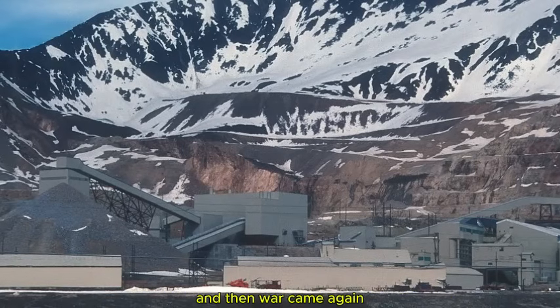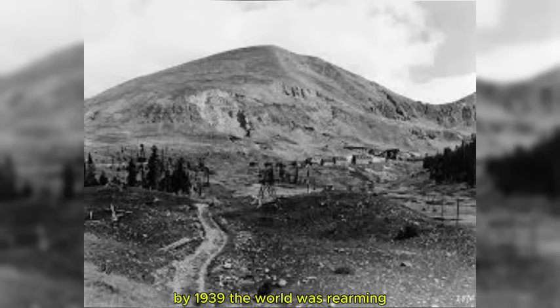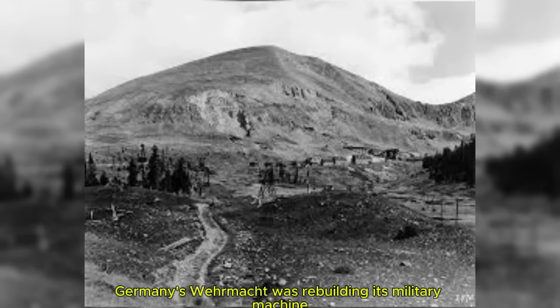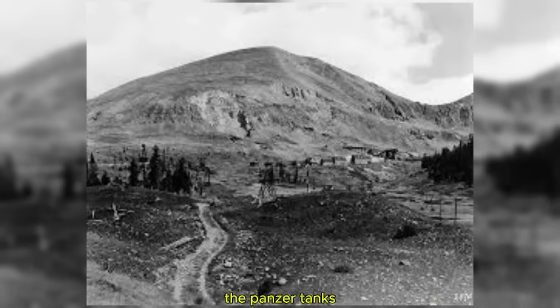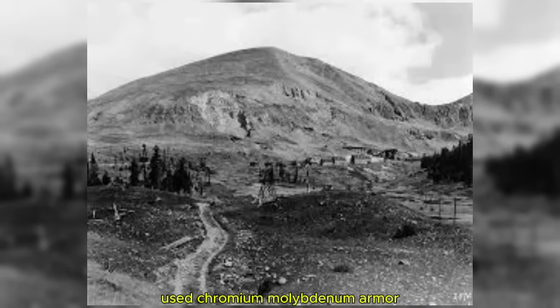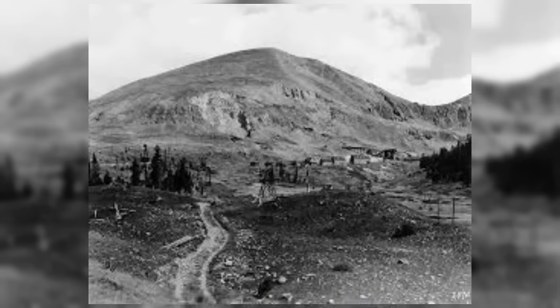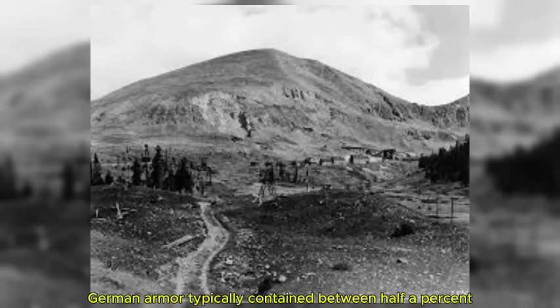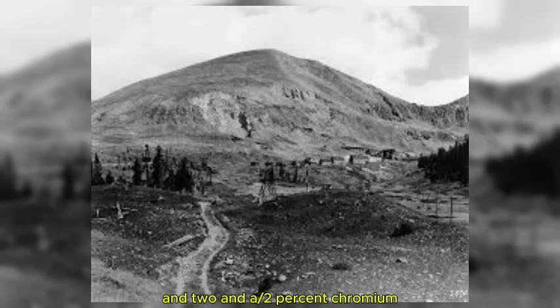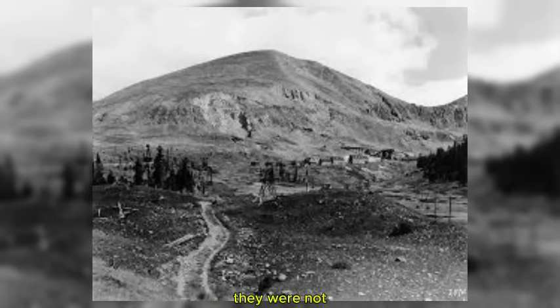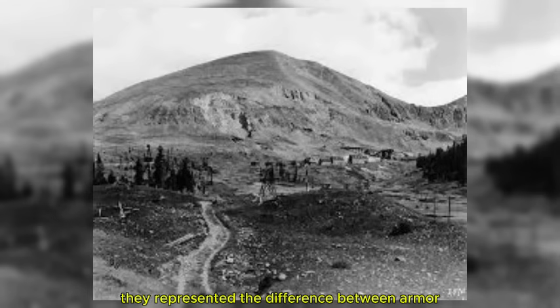And then, war came again. By 1939, the world was rearming. Germany's Wehrmacht was rebuilding its military machine on a foundation of molybdenum steel. The panzer tanks that would blitz across Poland and France used chromium-molybdenum armor, a combination that made the steel hard enough to stop small arms fire, but tough enough to absorb the impact of anti-tank rounds without shattering. German armor typically contained between 0.5% and 2.5% chromium and 0.25% to 0.5% molybdenum. These sound like small numbers. They were not. They represented the difference between armor that stopped a shell and armor that shattered into lethal fragments.